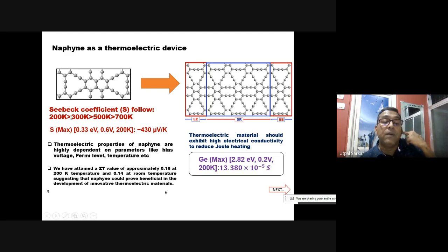That Seebeck coefficient at a particular temperature we have calculated, and we have found the Seebeck coefficient at 200 degree Kelvin is greater than at 300, 500, and 700, and these are the scale values. So thermoelectric properties of Naphyne are highly dependent on parameters like bias voltage, how much bias you are giving, where the Fermi level is, and what is the temperature at which you are measuring. You have found the ZT value of this particular material is 0.16 at 200 degree Kelvin temperature, and at room temperature it is 0.14, suggesting that this Naphyne could be beneficial in the development of thermoelectric material.